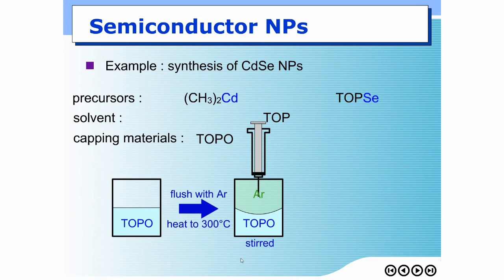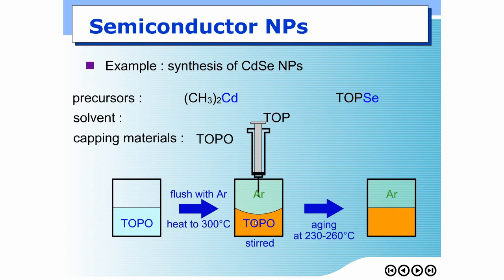Why do we stirring? The stirring here ensures the dispersion of precursor uniformly throughout the system, so that the nuclei that is formed will be capped by capping agent right away. Alright? As reaction proceeds, the particles will be formed. Nucleation occurs initially, following by growth. Okay, you see that the color would change. Then this is the first steps of the reaction.